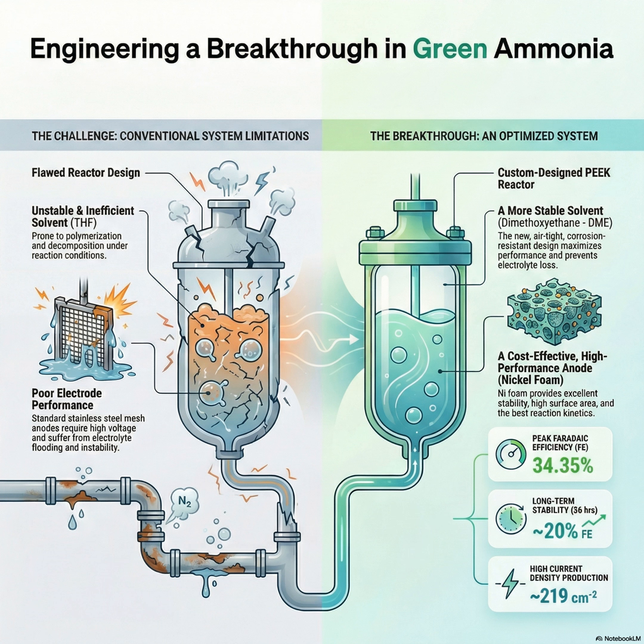No way. So they systematically tested other materials, and they landed on nickel foam, used for both the anode and the cathode. Nickel foam. What makes that so special for this? The foam structure gives it a huge surface area, which is great for reactions, and it's structurally very stable. But the key is, they proved it was better electrochemically using something called Tafel slope analysis. And what does the Tafel slope tell you? It basically measures how fast the reaction gets when you change the voltage. A lower number is better. It means the reaction's more efficient, the kinetics are faster. And the nickel foam had the lowest number. It did. It came in at 0.18 volts per decade. Wait, what was the expensive platinum one again? The platinum-coated mesh was 0.199. So that small sounding difference, it's actually a huge deal.